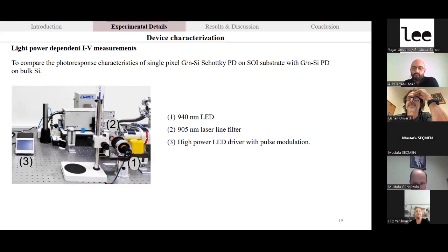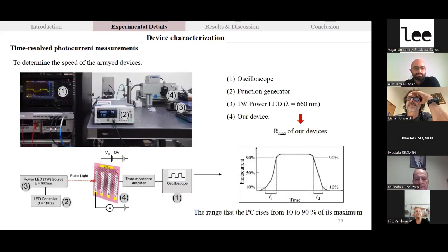The reference detector is the graphene n-type silicon Schottky junction fabricated onto bulk silicon. Here we use the LED source, laser line filter, and a high power LED driver with pulse modulation to get information about the power dependence of our devices. And we continued with the time-resolved photocurrent measurements to determine the speed of the arrayed devices.